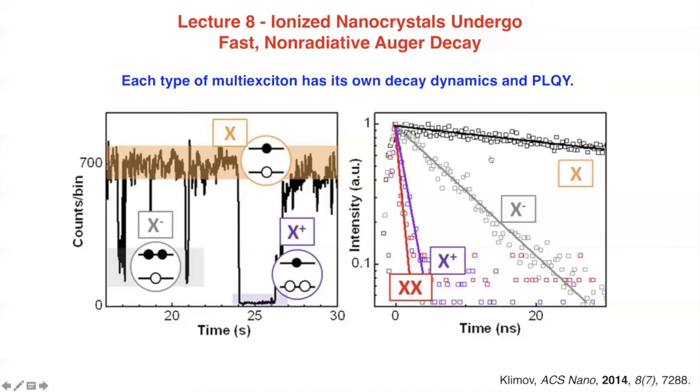And so Klimov says these two different gray states arise from negative trion and positive trion recombination. And then there's also a little bit of biexciton formation in there. And he partly knows this because they have independently measured these individual rates, and so they have a rough idea about how fast each of those different excitonic states does luminescence. And so this decomposition into these various states, mono and multi-exciton states, becomes possible.